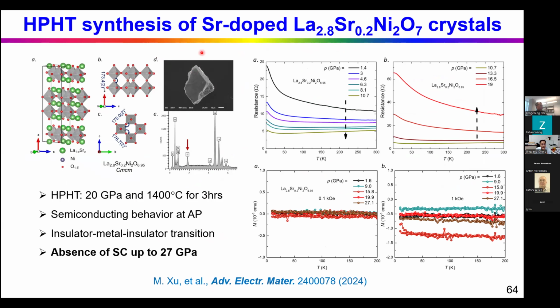they synthesized strontium doped bilayer nickelate. In this paper, they used high pressure, high temperature synthesis. They can increase the strontium content to around 0.2. But for this sample, they found under high pressure, the resistivity first decreases and then increases. And there's no superconductivity up to at least 27 gigapascal.